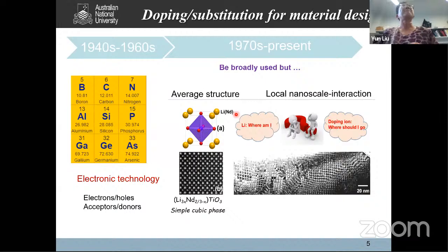Here I give an example. If we use X-ray powder diffraction to determine the structure of a material, it is pretty much the average structure over micrometers. That means your individual atoms may never be at that lattice site. Take lithium neodymium titanate, which is one type of lithium battery material. Its structure is a simple cubic phase with titanium-centered octahedra and oxygen at the corners forming the framework. In the cages of this framework, lithium and neodymium occupy one lattice site randomly. That's the picture you get from the average structure.